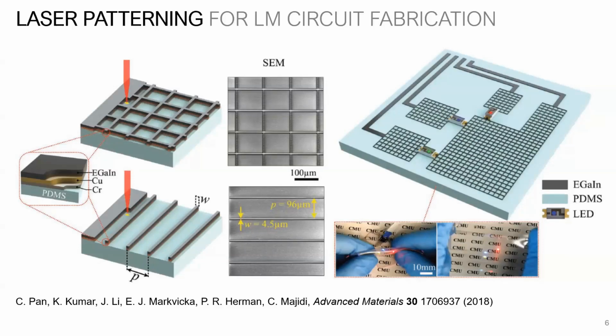We've found that probably the most reliable and best approach, at least for us, is to use UV laser micromachining. We just use an LPKF ProtoLaser. It's intended for PCB prototyping, and we just apply it to liquid metal. The key here is that we deposit the liquid metal not directly on a soft rubber substrate, but instead on a really thin, nanometer-thin film of metal, typically chromium and copper. You could also use gold. Then we deposit liquid metal on top of that and use this laser ablation technique to create the circuits.